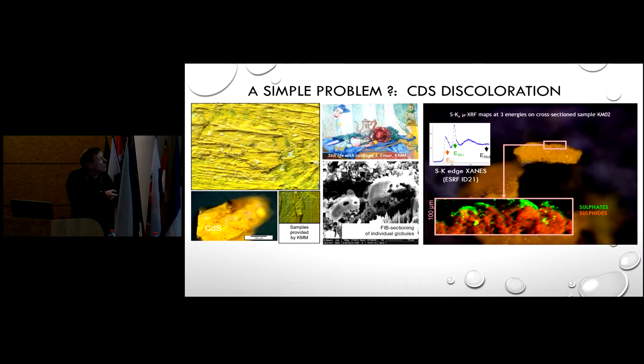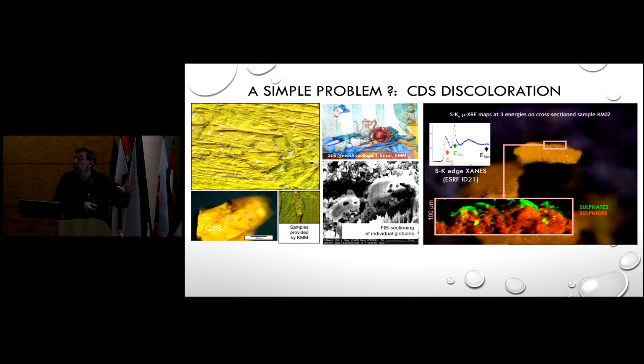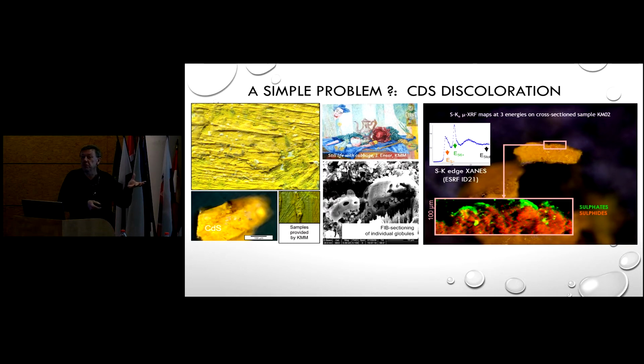Well, some yellow areas of paintings, like this Antwerp painting, showed a superficial precipitation which is colorless to white. And this is from a museum in Holland. And Joris Dik, who I knew by then, had tried in Delft, which is a technical university and very well into material science, to use TEM to figure out what this white powder was. And this didn't work because the electron beam evaporated the white powder. So very destructive, a lot of energy dissipation there.